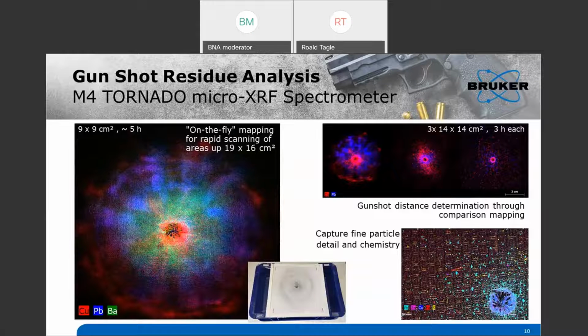In principle, the measurement conditions may change the total acquisition time a lot. That's not fixed. It depends a lot on the application. If you're looking, for example, at a major element, just a short measurement of, let's say, a few minutes, depending on the area that you're looking at, may be enough. In case you're looking at trace elements and very, very small variations, you might require longer measurement times, let's say an overnight measurement or even a weekend measurement.